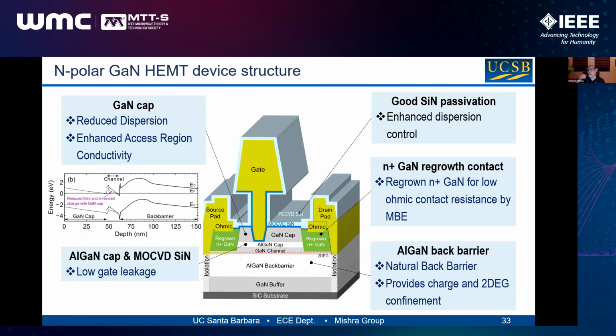So what we decided to do was increase the watts per millimeter, make the thing smaller, and increase efficiency. And we did this, and Umesh Mishra talked about this yesterday. We did this thing where we flipped the device, and when we flipped the device, we could get this two-dimensional electron gas with very high conductivity. But the beauty about it, we could put a gallium nitride cap on top, so we buried it. Okay, when we buried it, because of the polarization charges and the electrostatics of the system, it turns out that by doing nothing, just by growing GaN on top, we could increase the number of electrons in this channel. Just by adding some GaN, the electrons in the channel, no doping. Okay? This is just by playing with the polarization physics, you could add charge in the channel. And we could do regrowth to get good contacts. And then we did a gate to get the right aspect ratio to get gain.